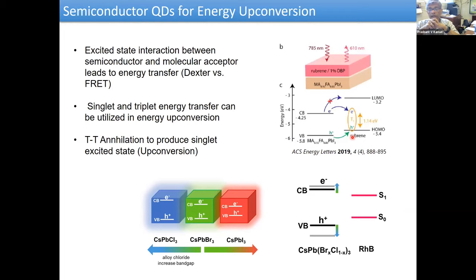Another one, this is our current interest, we are working on semiconductor quantum dots for energy upconversion and also transfer. So this is another area where you can combine a dye or a molecular sensitizer with the perovskite nanocrystal and study. In this case, it's a methyl ammonium formamidinium lead iodide, it cannot transfer energy to the singlet. Instead, it transfers energy to a triplet and generates a rubrene triplet. And the two triplets combine to give you a singlet excited rubrene. So that's why, although you are exciting at 785 nanometers, you can get emission back at 610 nanometers